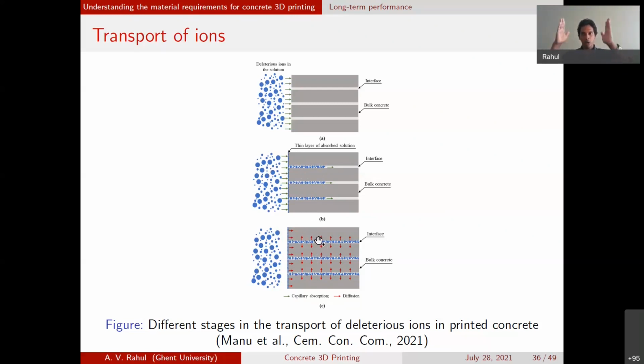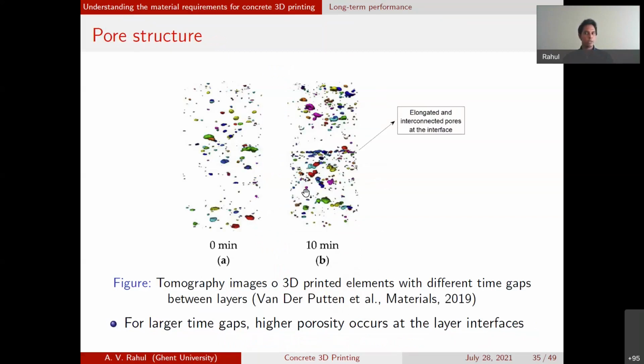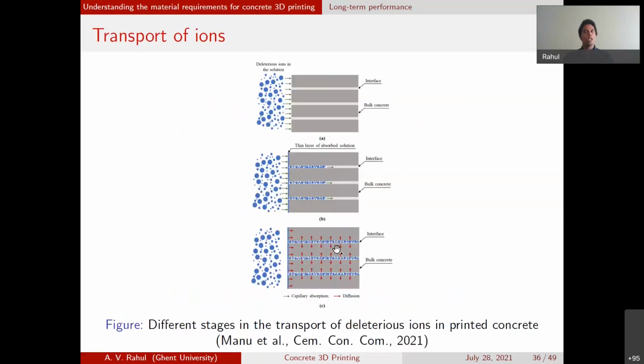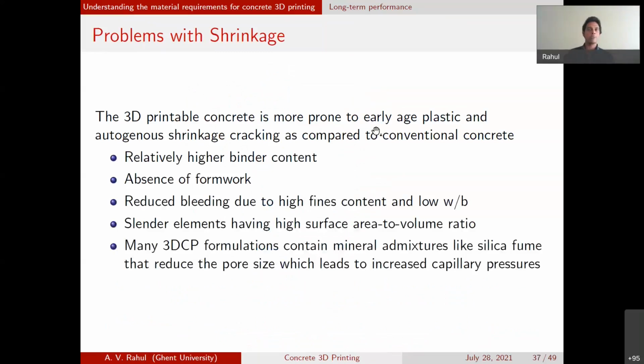So initially, a small layer is formed through capillary absorption, and then further ingress can occur through diffusion of these ions into the concrete. But this is a hypothesis, or a possible scenario that may exist based on the published literature that was presented in this work. Further studies on this are required to really know what the likely service life will be with 3D printed structures. One other critical problem that we need to point out with printed structures is shrinkage.